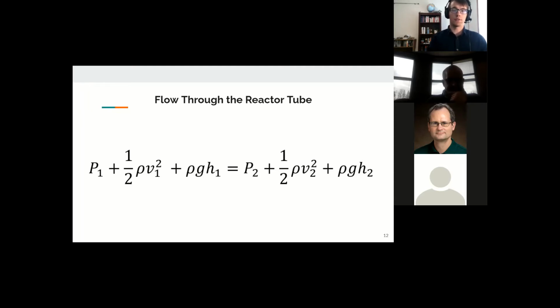So this shows that for a larger diameter reactor tube, the gas flows slower through the pipe. Generally, to make homogeneous powders in this system and reduce reactor wall deposition, a larger diameter glass reactor was chosen. This reactor measured 0.69 inches in inner diameter and 1 inch in outer diameter, making the wall about 0.16 inches thick. That's a really thick wall. Such a thick wall allows for high plasma power to be used, which is important.